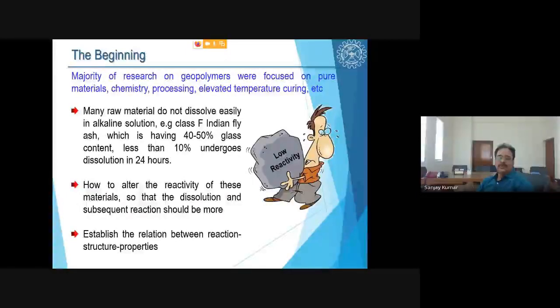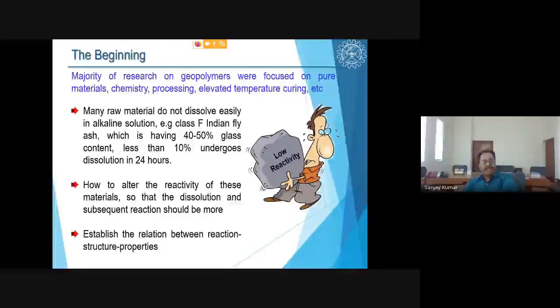So we tried to focus on reactivity, and the immediate concern was fly ash. In India, we get mostly class F fly ash. It has 40 to 50% glass content. But even in this 40 to 50%, if you put it in the alkali solution, only 5 to 10% undergoes dissolution. This is because of the poor reactivity. That is why we thought reactivity was going to be a very important area. So the question was how to alter the reactivity of this material so that the dissolution and polymerization and everything would be more and faster. And then we thought we would try to establish a relation between reaction, structure, and property in geopolymers.